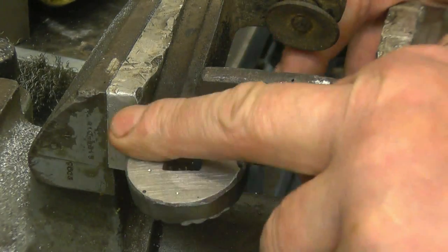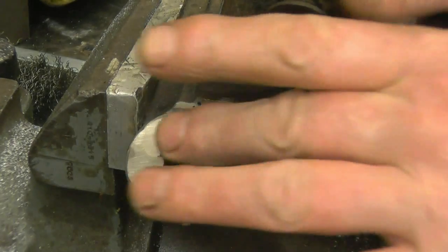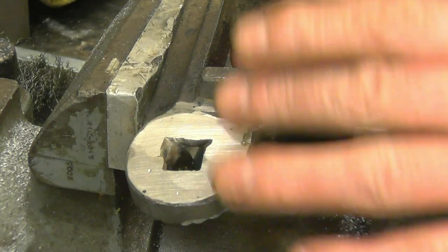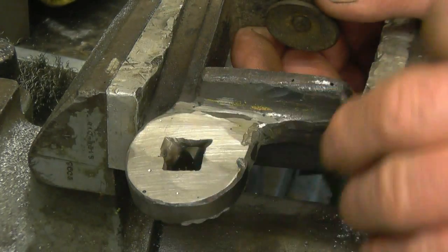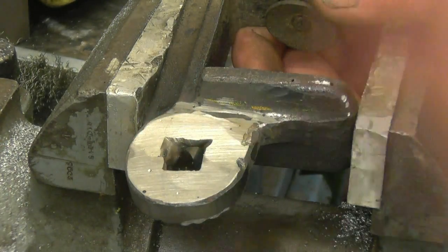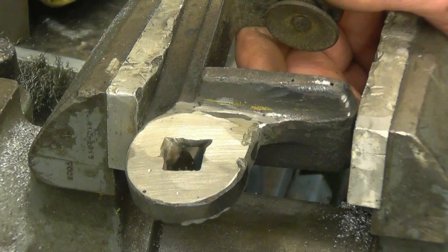I've machined the weld off here. Well, when I say machine the weld, I've actually had a bit of a tickle at it with an angle grinder. So I've machined the weld off. You can see where the weld metal is in there. There's no signs of it cracking. It's a nice strong repair.